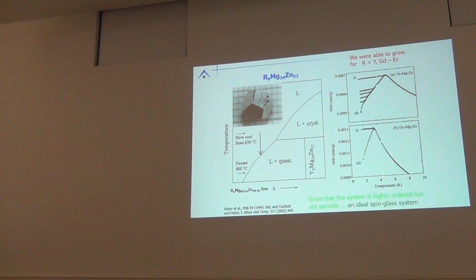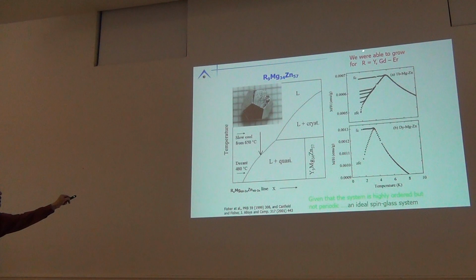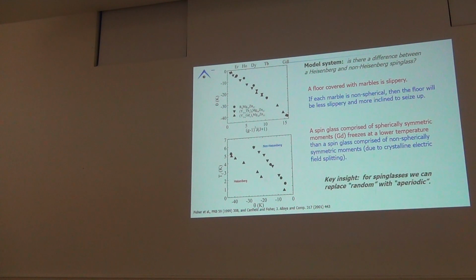We can do physics. We measured the magnetic properties. What happens is, with a rare earth on an aperiodic sublattice, we found that these were classic examples of spin glasses. Okay? It's not surprising you have a large degree of frustration because your nearest neighbor distances have a wide range of values on this aperiodic sublattice. You don't have periodicity, okay? So they were model spin glasses. With model spin glasses, you could ask sharp questions.